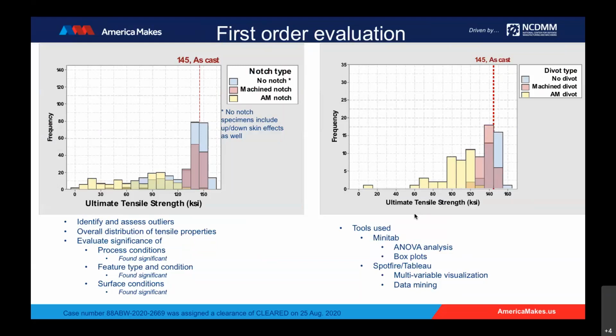One of the biggest takeaways is that from the AM samples, we see a decrease in performance and also a very big variation in overall performance. Now, if you were to compare it with machine notches or machine divots, you see much less scatter in performance and also a slight improvement in performance. So here, one of the biggest takeaways is that operating with the AM surface finish could significantly diminish your performance. Right. Next slide, please.